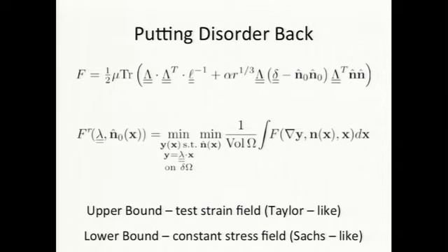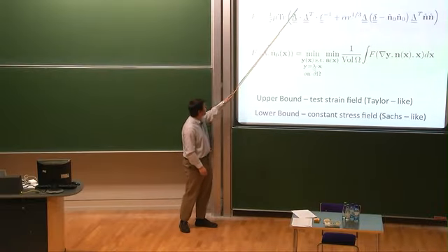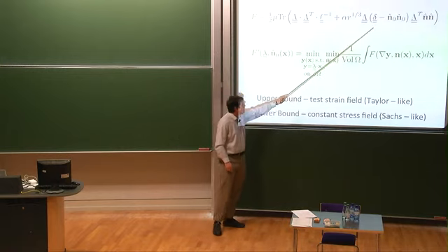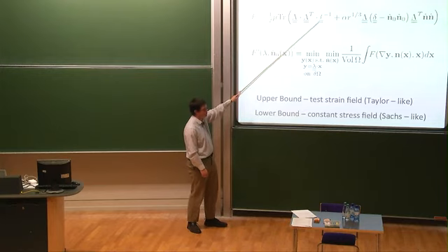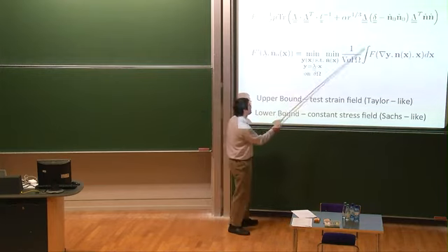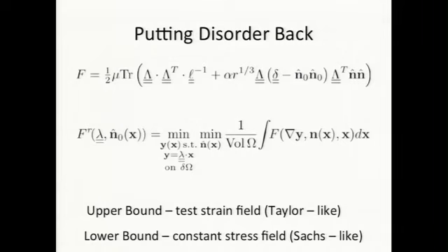So where do we get these test strain fields from? Of course you can choose anything, but the ones that we use, which gave fairly good answers, are the domain structures posited by Antonio, which minimize this part perfectly. Then you just evaluate their energy with this part. So we choose the domain structures which minimize the dominant part of the energy completely. And it's easy to evaluate how much energy penalty they incur from this part, because these domain structures don't correlate with n0 at all. So assuming almost nothing about n0 other than that it's isotropic and random, you can work out the averages there very easily.